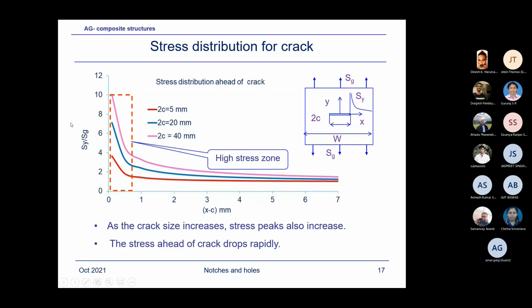Whereas we saw for the hole edge, right over here, x equal to 0, right? So here, x minus c equal to 0, the value sigma_y upon sigma_g does not change. It remains the same. Like for quasi-isotropic or isotropic it is 3, whereas for the crack, it is a different value.